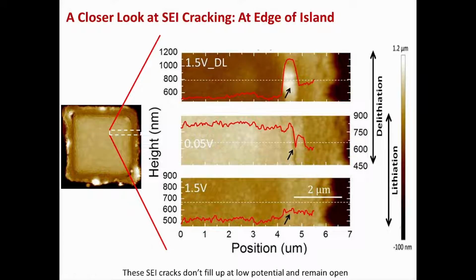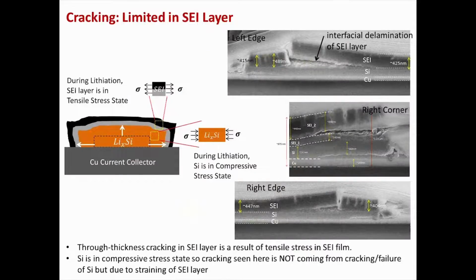So two things to take away from these two slides: the cracks, once they form, don't completely fill up with new decomposition products, and we can in situ and operando monitor this crack formation by applying this AFM technique from Bruker. One thing I want to mention very carefully is that these cracks are not coming from the underlying silicon, because while we are lithiating silicon, the lithiated silicon is under compressive stress. So any crack would not form in the underlying silicon. Because of the stretching of the SEI layer, the SEI layer is in tensile stress mode, and that's why it results in tensile strain and cracking of the SEI layer.